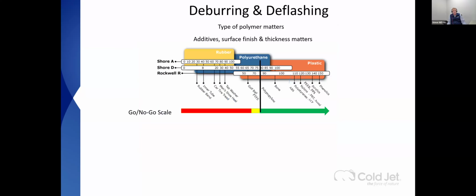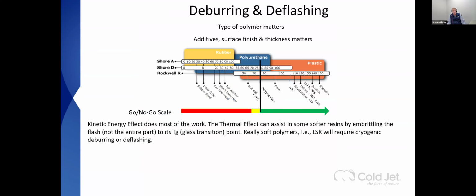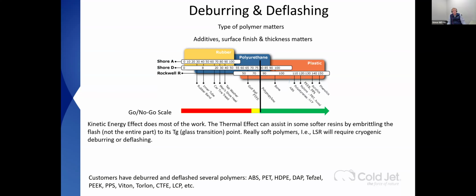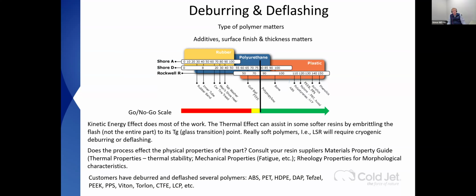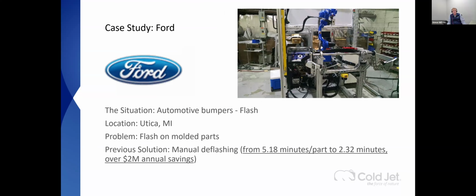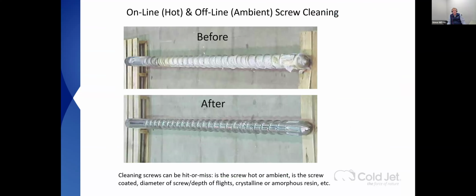Just for reference parts, I'll give you a go, no-go scale. You're going to deflash parts generally on the kinetic energy side of this. The thermal effect can assist, maybe even brittle sometimes to get to the Tg point of the flash. Polymers about 85 Rockwell R and above do well. Those below sometimes absorb kinetic energy and they struggle. And depending on how long you stay on the part, how much thermal properties you put into the part, grab your material property guide and look up the thermal properties of the resin. Ford saved $2 million a year deflashing, switching over to dry ice, removing labor parts.